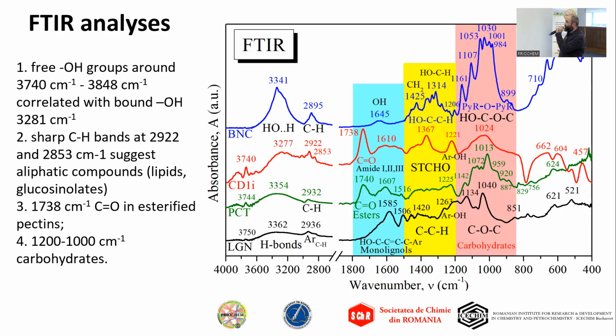The infrared spectroscopy can reveal particular absorption bands. In this case, we compare the cabbage treated with dose 1, in red, with bacterial nanocellulose as representative for 1 alpha cellulose, pectin, and lignin. Specific for pectin are the COO bonds in esterified pectin, which we found also in cabbage samples, while for cellulose the bands are related to structural carbohydrates.